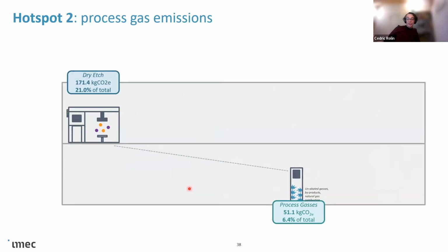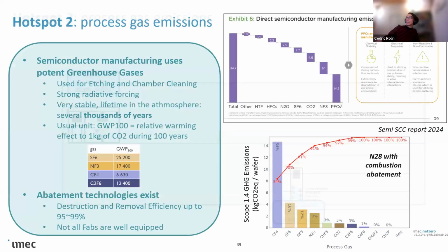So the industry is actually using a lot of fluorinated gases, and those fluorinated gases have a high global warming potential. So when you release, let's say, one kilogram of that gas, it will have a high climate impact. And this is mainly related to the dry etch process area, which is the one that is using this type of gases. We show here that there's about 50 kilograms in this 28 nanometer logic node example that is related to the direct release of those gases.